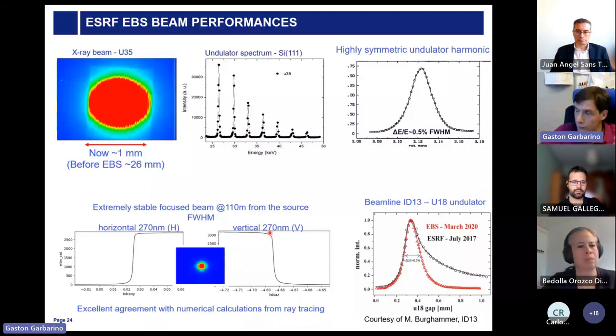So we are really able to probe samples with applied pressures of the order of 3-4 megabars, 3 million atmospheres. At the same time, we now have harmonics in the X-ray generation that are much narrower and very symmetric. That means we can use the full harmonic to do diffraction, meaning we will have much more flux, but at the same time we will not degrade the quality of the diffraction.